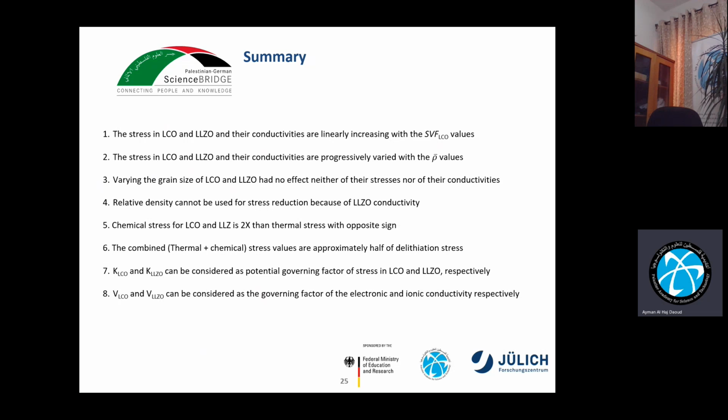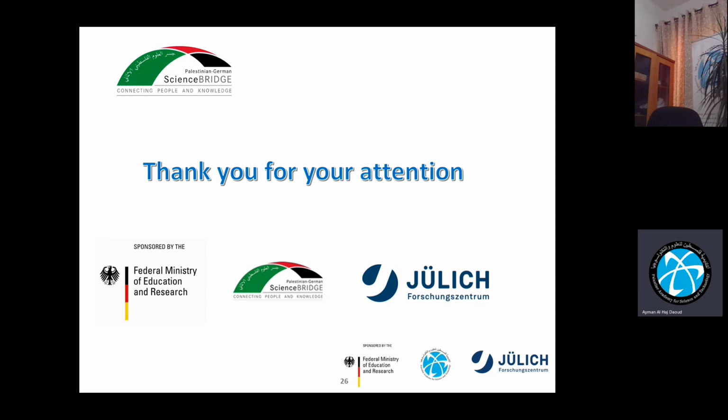KLCO and KLLZO could be considered as potential governing factors of stresses in LCO and LLZO respectively. And finally, the volume fraction of LCO and the volume fraction of LLZO could be considered as governing factors of electronic and ionic conductivity respectively. To this point, I finish my presentation.